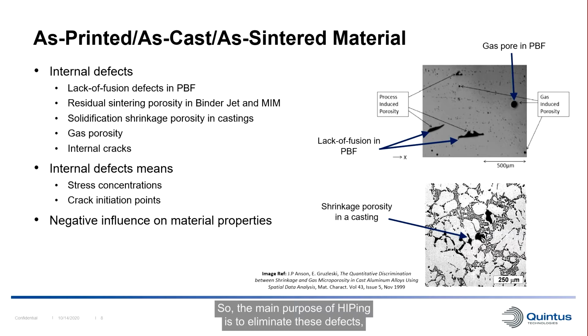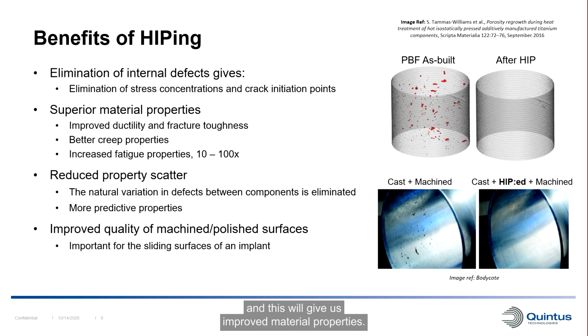So the main purpose of hipping is to eliminate these defects, so you eliminate the stress concentration and crack initiation points. And this will give us improved material properties. For example, improved ductility and fracture toughness, better creep properties, and especially improved fatigue properties. We normally also see a reduction in the scatter of properties.